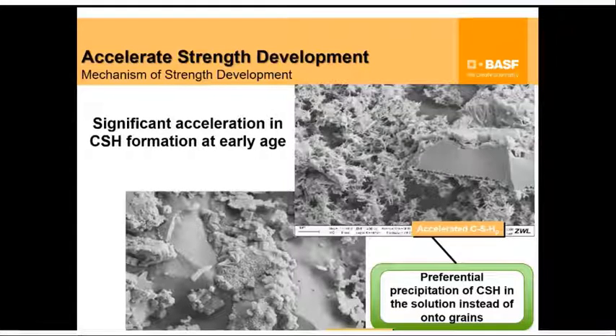On the top right is a cement surface at the same age, but using a strength accelerator. And you can see more CSH being formed all around the cement particle, which is in the middle here in gray. And like I said, you can induce higher CSH generation using these chemical nuclei to get very early age strengths.